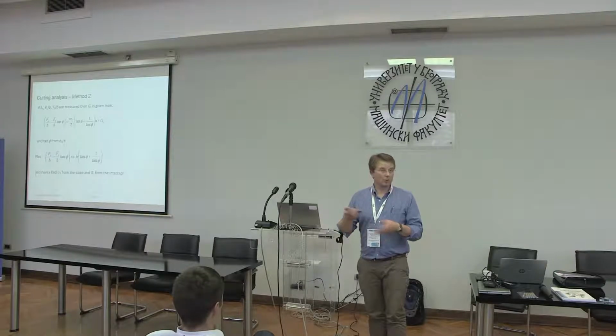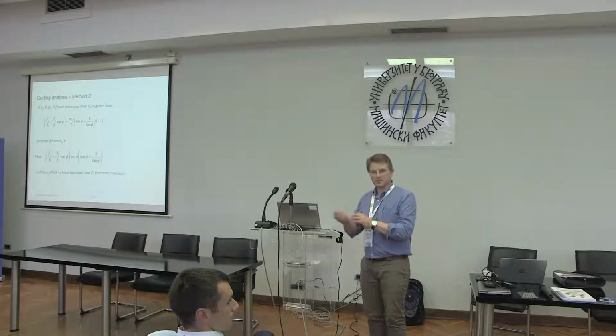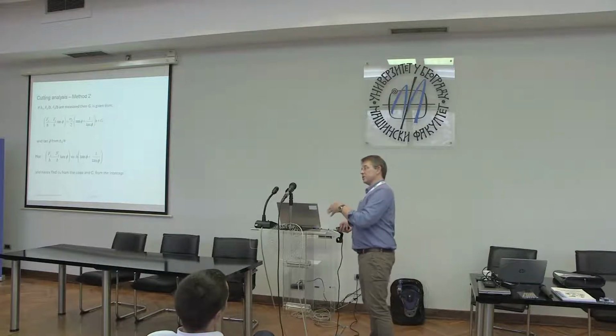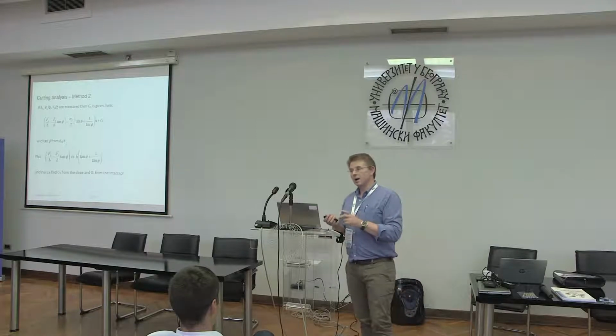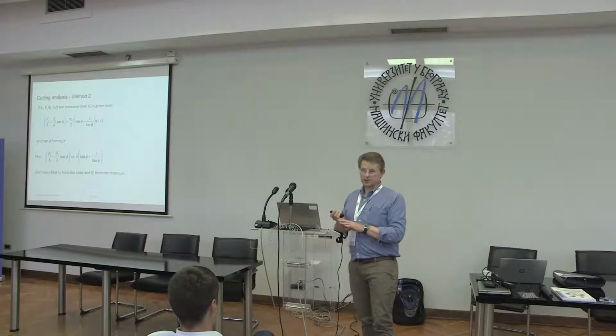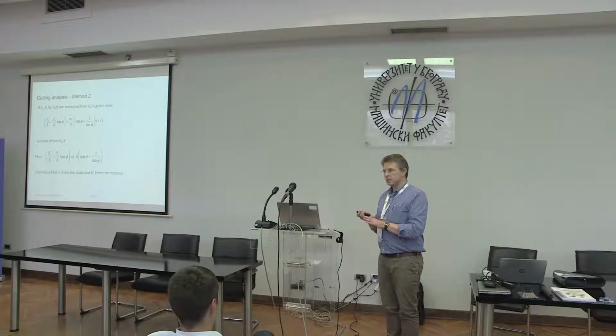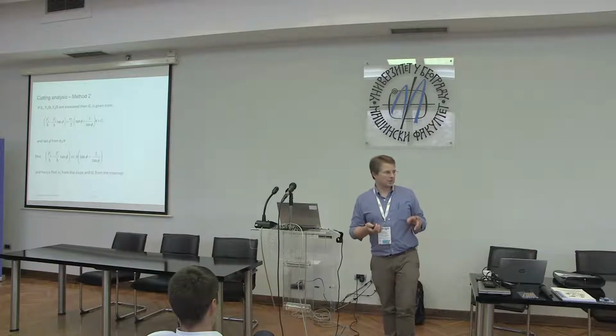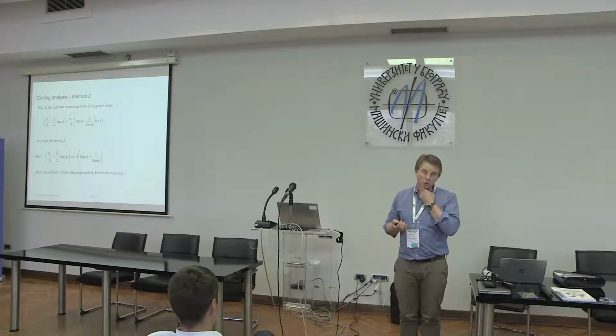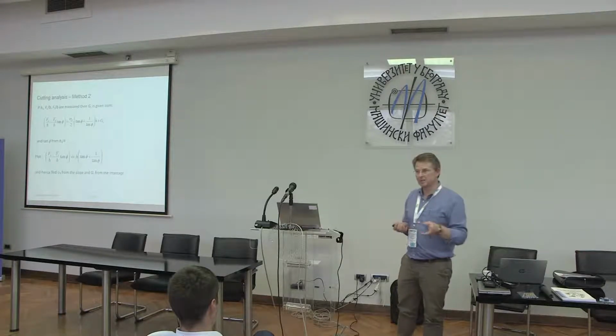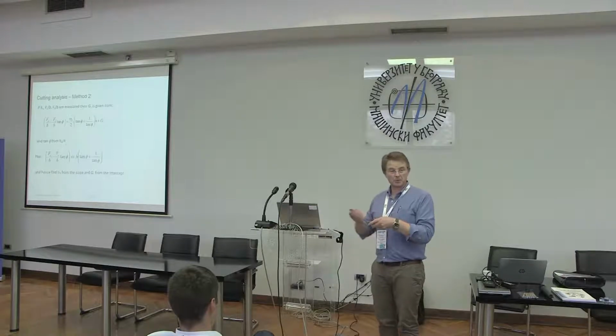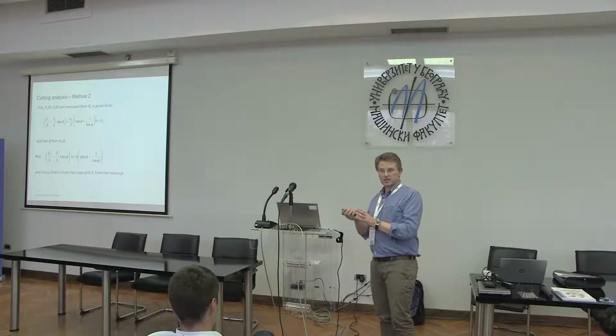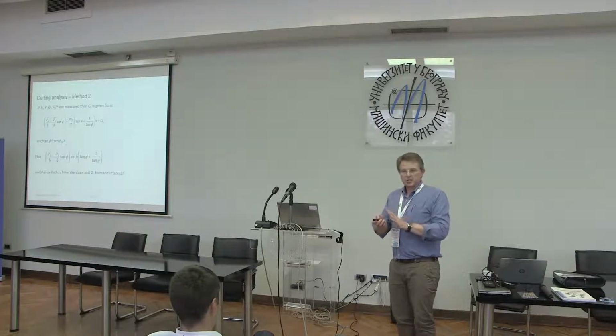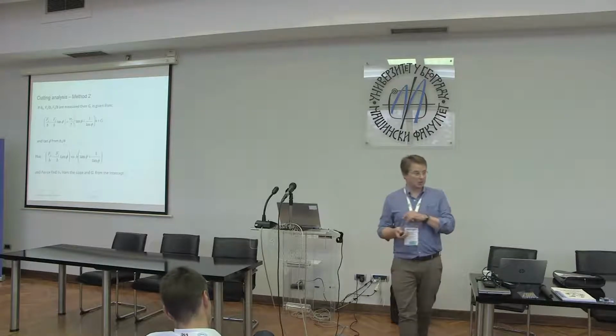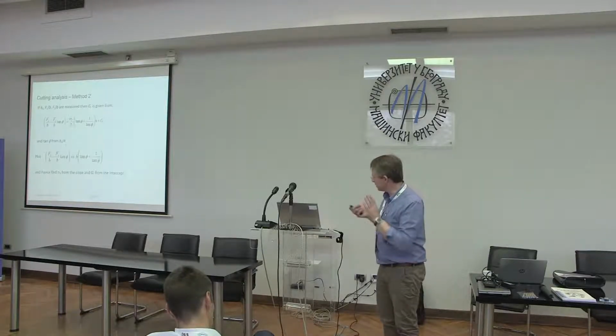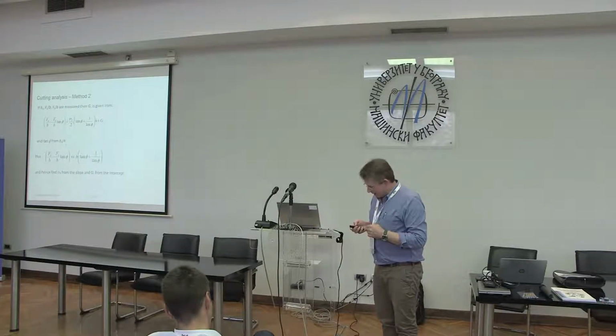In fact, in the published work we had 4 methods where we also considered the conditions of the interface. If you do consider the different conditions on the interface between the chip and the workpiece, you can of course measure input or output coefficient of friction depending on which way you want to go. What we found was necessary if we're considering the interface between the chip and the tool was the adhesion between the material. Okay? We found that friction on its own wasn't able to explain what we saw, so there must be an adhesion term. So it was actually the polymer sticking to the tool, and we put that adhesion term in and got some quite interesting results. But it's not what I'm going to be talking about this morning.